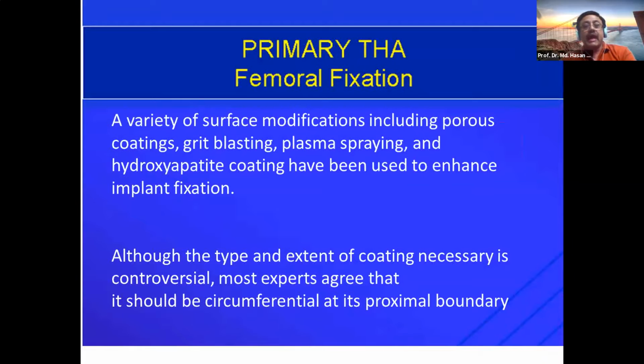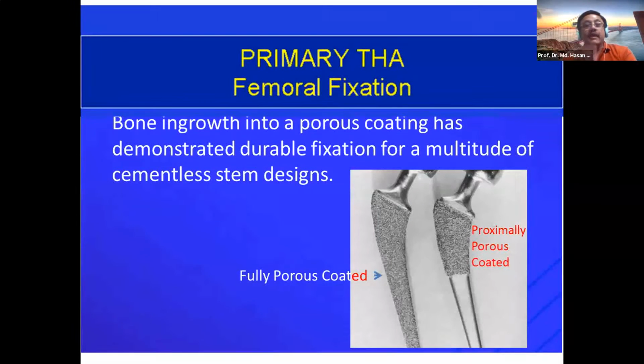Although the type and extent of coating necessary is controversial, most experts agree that it should be circumferential at its proximal boundary. And you see bone growth into a porous coating has demonstrated durable fixation for a multitude of cementless stem designs. And porous coatings have historically been created by either beads or fiber mesh applied to the stem by sintering or diffusion bonding processes. See here, it is the fully porous coated, and this is the proximally porous coated.